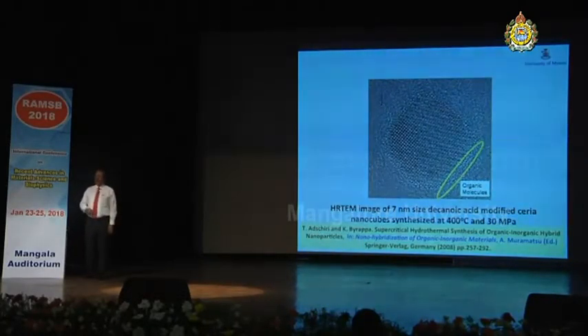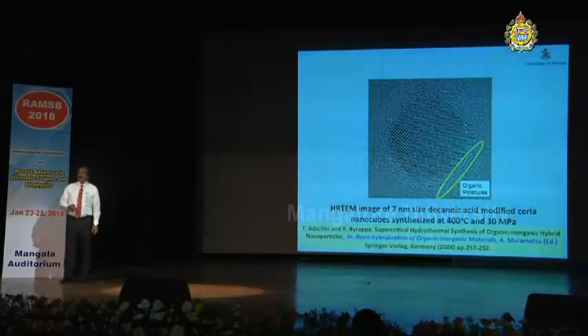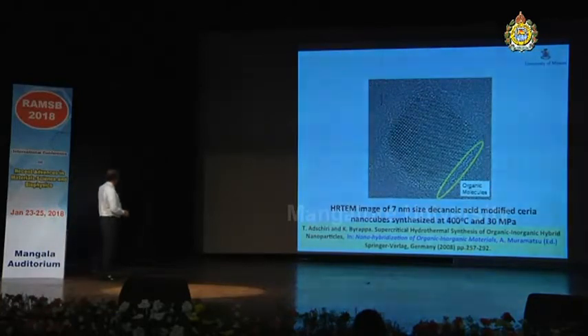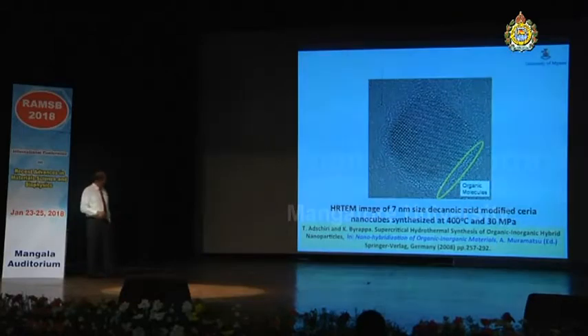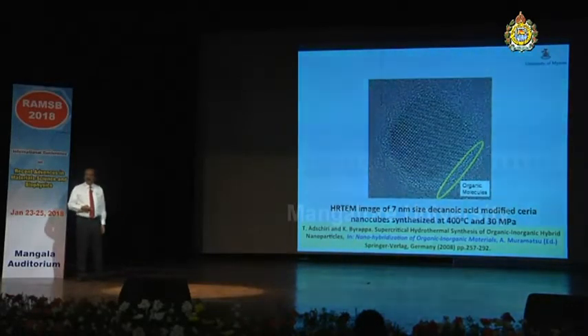And you may ask how thick these organics coating over the metal oxides are. This is the high resolution TEM image of ceria nanoparticles of about 7 nanometer size, obtained with decanoic acid as a surface modifier, and the nanocubes are arranged so well, and you have a very thin layer of organic here, which you can remove through sintering at around 500 degrees C. The organics can be eliminated, but still you can retain the same size and shape for these nanoparticles, and also unagglomerated.